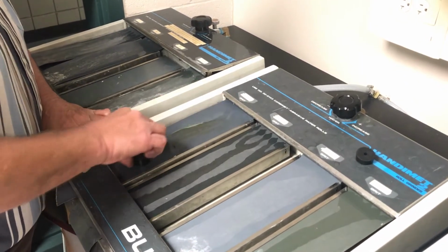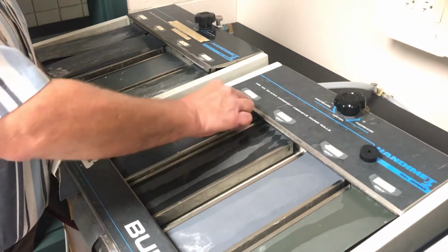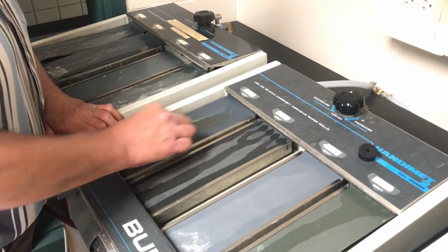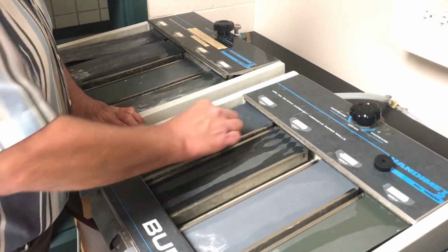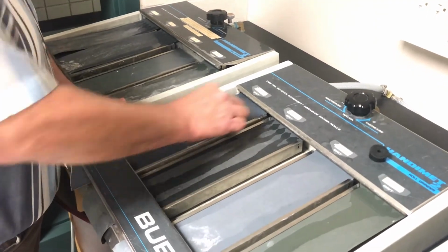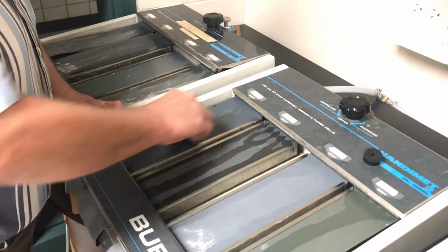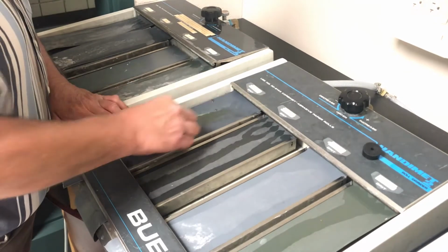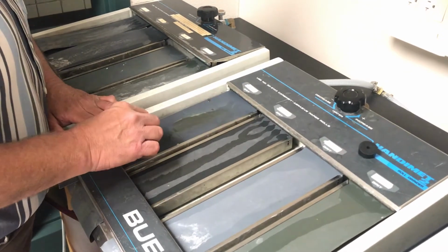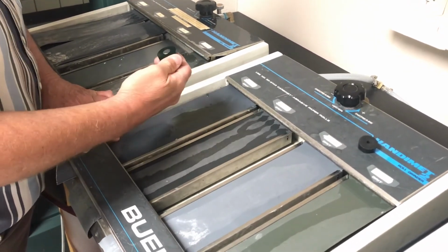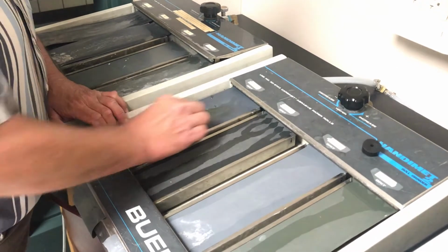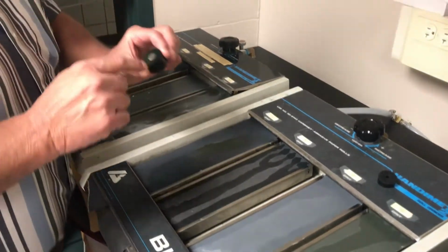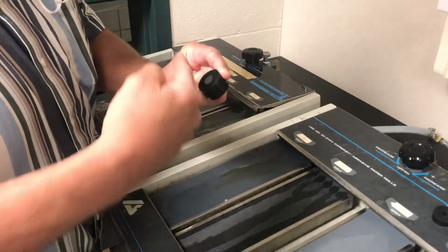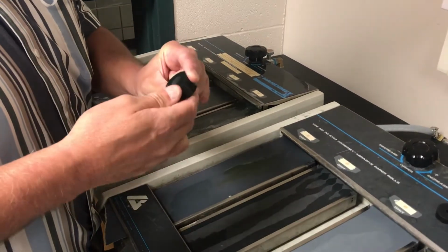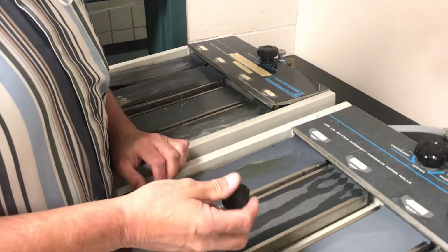a series of strokes on the 320 grit paper. Go in one direction rather than back and forth. Just go one, and generally on the order of 12 to 20 strokes will accomplish what you want. You can look at your sample and see that all the scratches are moving in the same direction. That tells you you're making progress, and you can move on to the next step.